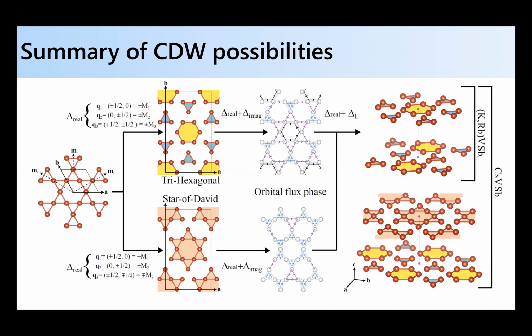Yeah, I think in an ideal case, neutron scattering would be great. But you need a momentum resolved probe that could couple to time reversal symmetry breaking. And there's some technical challenges with neutrons that have to do with the sample size, but also with the moment size. So the moment, if this state is present, is certainly very weak, and it's potentially just beyond the resolution of standard neutron diffraction, let alone polarized neutron diffraction, which you would really want. So potentially resonant X-ray scattering, like on the vanadium edge, could be done. It may require some creative thought. I haven't thought about whether or not you can actually reach the right Q vector with the vanadium L-edge resonance. So there might be some ways of doing it with resonant scattering. I think that's probably the most promising for a momentum resolved probe.